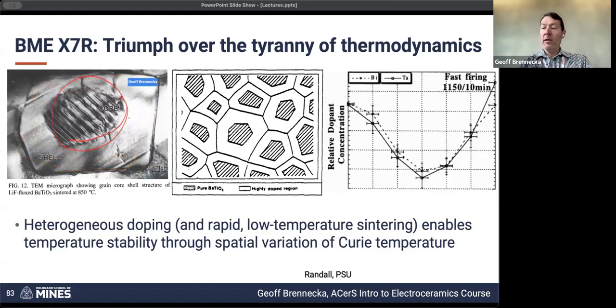The inner core is in its tetragonal form, and you can tell that from the twinning. Those are domains that we're able to see there. They're essentially martensitic twins that form when you cool it down from the cubic phase to the tetragonal phase, and you form these twin structures. We'll get into the domains and domain walls a bit later today or tomorrow or next week.